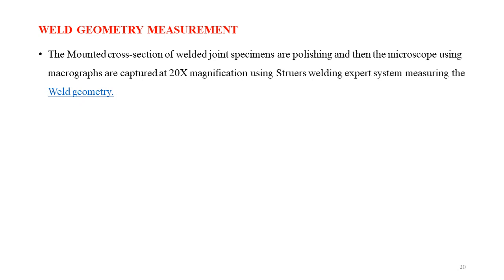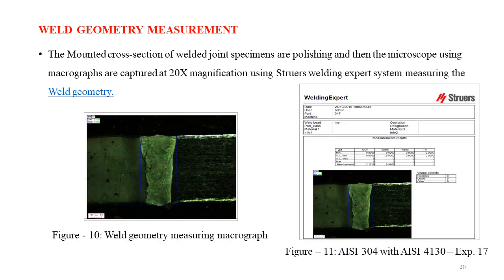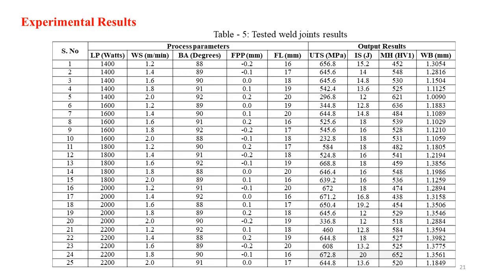Coming to bead width measurement, from the weld geometry measurement point of view, hot mounted workpieces are used here. Those workpieces are polished, and then the weld zone is captured at 20x magnification, and welding expert system software is used to measure the specimens. These are the welding samples, and we measure them, and then go for the experimental results.